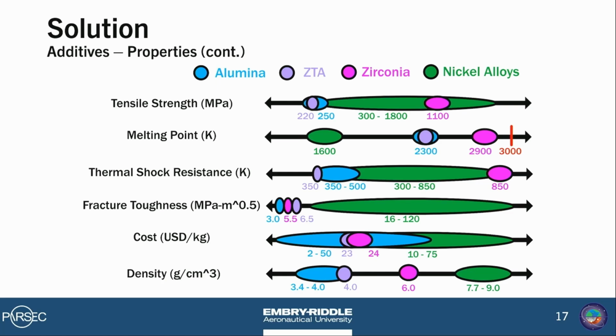Nickel alloys, their properties can range widely, and that's because their properties heavily depend on the specific alloy content. However, one thing that remains consistent among nickel alloys is their low melting point compared to the ceramics, which means they will melt a little faster in the plume. It's really important to have a diverse range of properties for our additives like this because it allows us to test the extent to which certain properties matter when forming a strong landing pad. Once we can determine the extent to which certain properties matter, we can begin to identify materials with more curated properties to better assist with this solution.